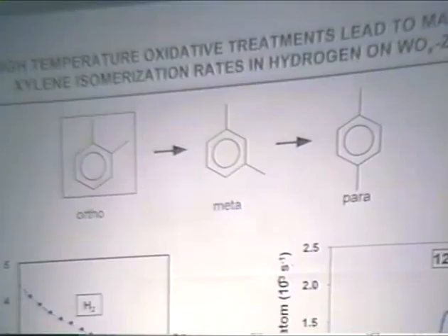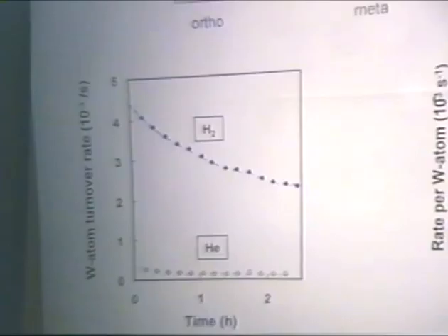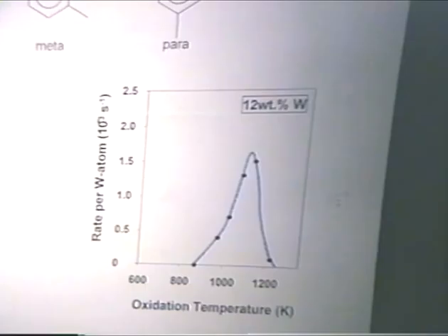We decided to move away from reactions of alkanes because of obvious complications, and to look at a very simple acid-catalyzed reaction: the isomerization of ortho-xylene, which should involve only protonation, deprotonation, and an intermittent methyl shift. We were able to reproduce a much higher rate of reaction when we carried out the reaction in hydrogen after pre-treating the material in hydrogen, than when we carried out the reaction in helium, requiring a calcination at about 800 degrees.